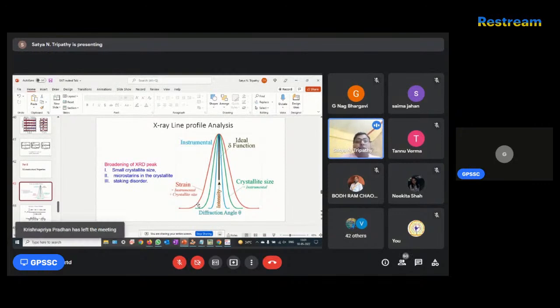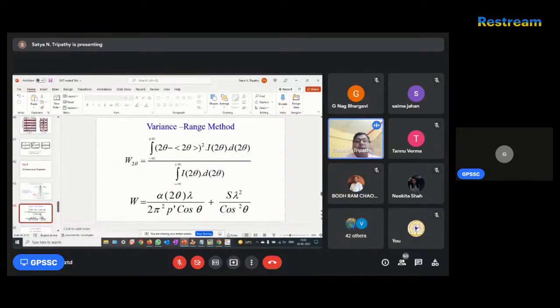So how are we going to calculate all this, right? First of all, the method is the variance range method. In the variance range method, we calculate the variance of the peak, and for that variance, we calculate the range. Here alpha is range, W is variance, cos theta is the angle, lambda is your wavelength, and S is the strain part. If you plot a graph between variance and range in 2 theta, you will obtain a straight line because this is a linear equation, and from the slope you can calculate the crystallite size.